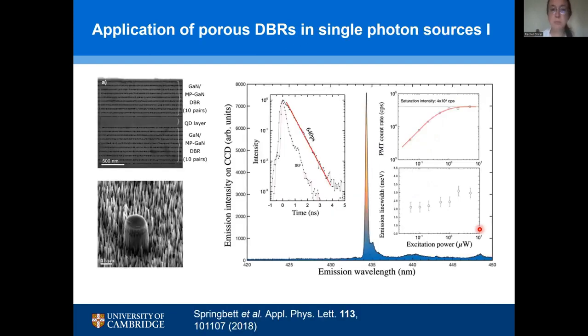We can also bring these porous distributed Bragg reflectors into more exotic devices. So as I say, when we started, what we wanted to make was a single photon source, and we needed DBRs for that. So this is one such single photon emitting device. So here we've got a quantum dot layer sandwiched between 2 porous gallium nitride distributed Bragg reflectors. And we milled that then into these micro pillar structures, which ideally would be beautiful cavities. They aren't as beautiful as we might like, particularly at the stage when this experiment was done. We hadn't really got the processing under control.